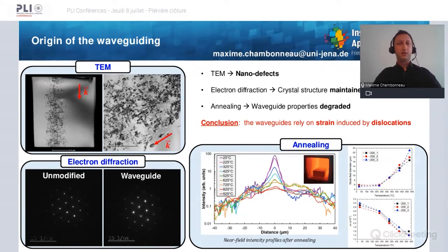Then, what is the origin of the waveguiding? Well, to answer this, we have carried out other measurements. First, with transmission electron microscopy, where here you can see some nano defects along the waveguide track. Then, with electron diffraction on unmodified and modified silicon, we have seen no difference in terms of crystallinity, so we concluded that the crystal structure was maintained. And more recently, we have carried out some annealing experiments at different temperatures, where we have seen that both the mode field diameter increases and the delta n, so the refractive index change, decreases with the temperature. So our conclusion is that the waveguides we have written rely on strain induced by dislocations.